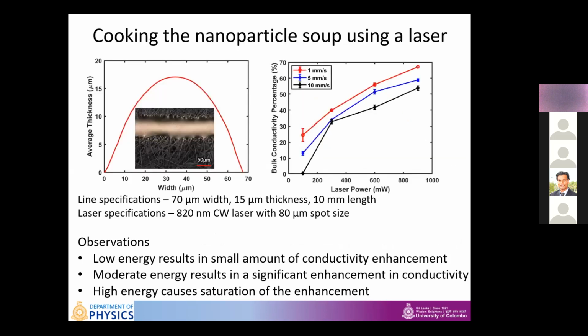Here I summarize some of our printing and cooking activities on paper substrates. The figure on the left-hand side shows a photograph of a printed trace. That's a silver nanoparticle printed trace. And also the cross-sectional profile shown in the red line on the graph. Approximately, this is about 70 micron wide, 15 micron thick, 10 millimeter long conductive trace.